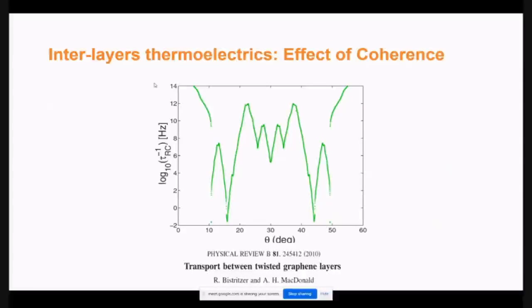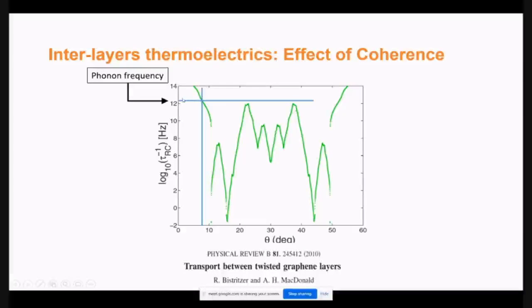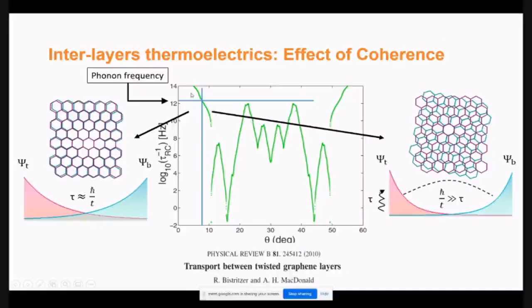Okay, and then you get this pattern. Now, if you look at the kind of range that we have, this is log to the base 10, the phonon frequency is somewhere here. And the corresponding angle is about 4 to 5 or 5 to 6 degrees, at which, for larger angle, the phonon frequency is larger than the electron tunneling or hopping rate from one layer to the other. Whereas when the angle between the two layers is small compared to this 5 or 6 degrees, phonon frequency is smaller and the hopping matrix element is larger between the two layers. So that kind of gives us the clue what is happening there.